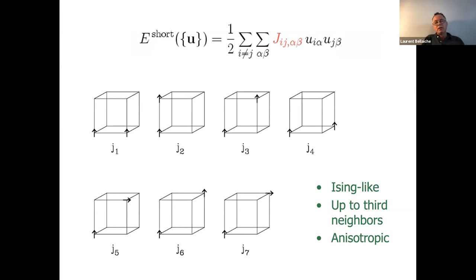You have J2. It's also the interaction between two dipoles along the Z axis, but the distance now is along the Z axis. And you have quite complicated ones as well, like J5 and J7. It's between different components of the dipoles and different nearest neighbors. J5 is second nearest neighbors. J7 is third nearest neighbors. So it's an Ising-like technique.